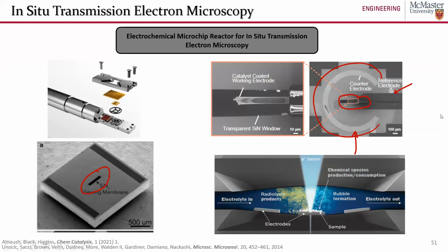Then looking from the side angle, we've got our working electrode here, where we have our active material illuminated at the top. In the case of transmission electron microscopy, our electron beam comes in, goes through our catalyst materials or our electrode materials, and then comes out where it goes to the detector. I apologize for my terrible artistic capabilities, but this illustrates why we need this very thin electrolyte layer. If it's too thick, these electrons are never going to be able to get in, and they're never going to be able to get out, and we're never going to be able to characterize our materials. So this is why we need these microchip reactors.